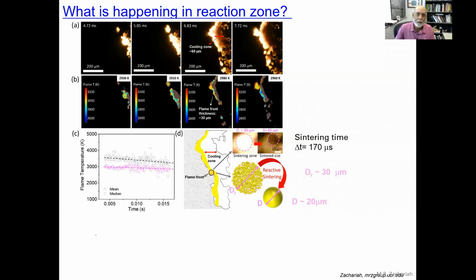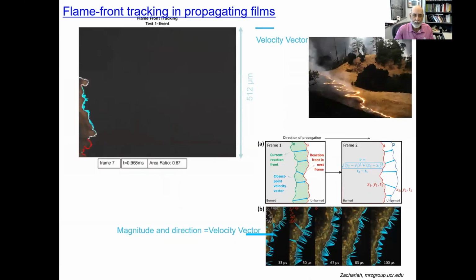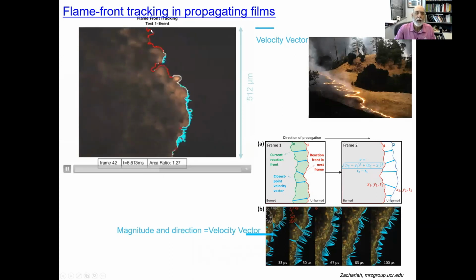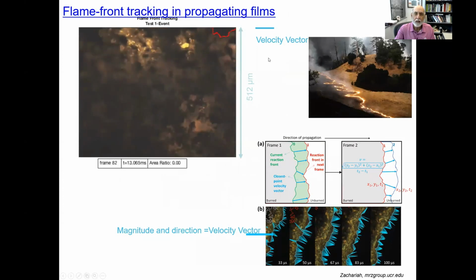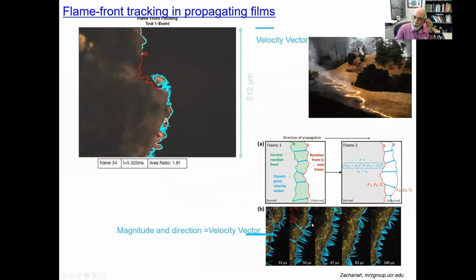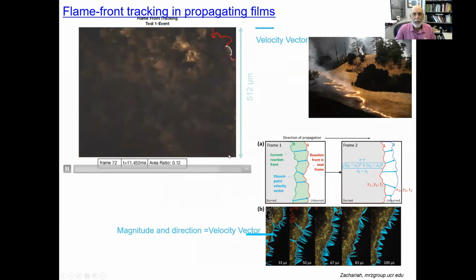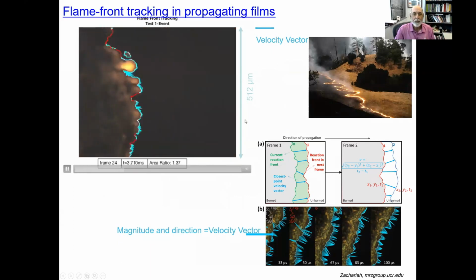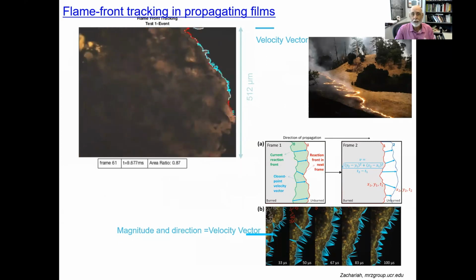So from this kind of information, we can get things like the thickness of the reaction front. What is the effective reaction volume? In other words, that creates the sintered particle size, because we know what this is from the post-inspection. So we can work backwards and get what is the effective volume of particles that's sintered and what their time scale in sintering is in this system. I won't go through those details, but we can also get the reaction front corrugation and the local velocity in the reaction front. So we can get the local microscopic velocities and compare that, when we integrate all the velocities, to the global average velocity that you as an observer see.